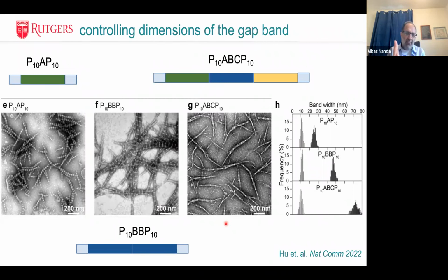In the absence of that V domain, you could imagine the 3 strands of the triple helix assembling in different sorts of offsets. You might get more heterogeneity in terms of assembly. So it does a lot to both control the homogeneity of the assembly, but also in nucleating it. But once you cut it off, the fiber stays assembled.